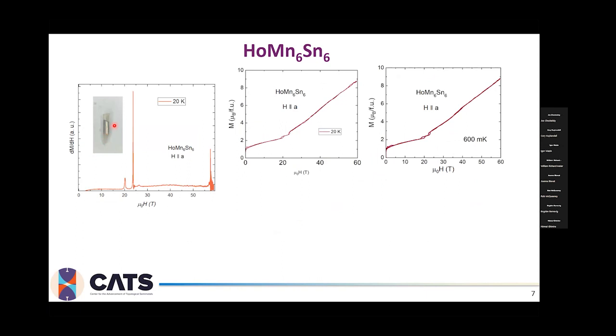To measure the magnetization in the high field, we put a small, tiny crystal into an ampule. That ampule has a diameter of around 1 millimeter. What we are actually directly measuring is the magnetic susceptibility. The advantage of this is that we can clearly see all the sharp peaks which reflect the metamagnetic transitions, which are much more visible in dM/dH than they would be in the magnetization. So it is very useful for studying phase diagrams. Over here, I can clearly see 3 peaks between 20 and 27 Tesla, which look much smaller in the magnetization. There is also a very clear sharp peak around 57 Tesla, which reflects a higher transition, and which is not that visible if we look at the magnetization.